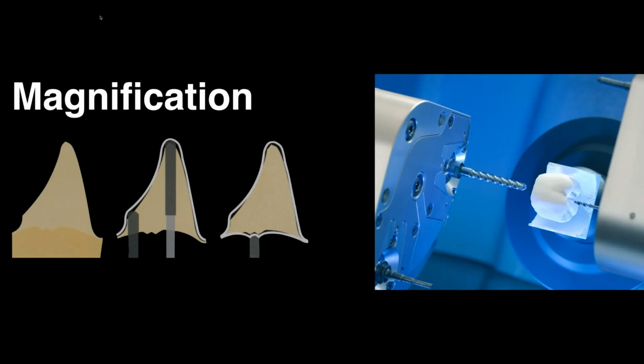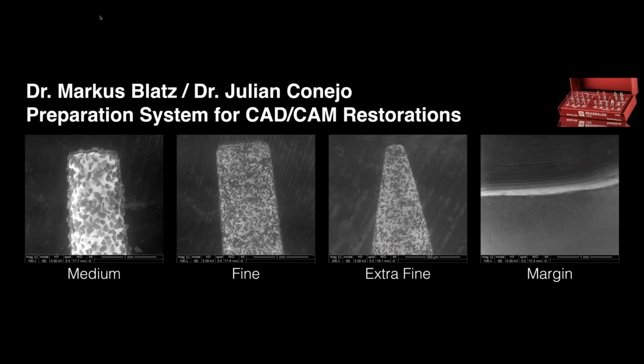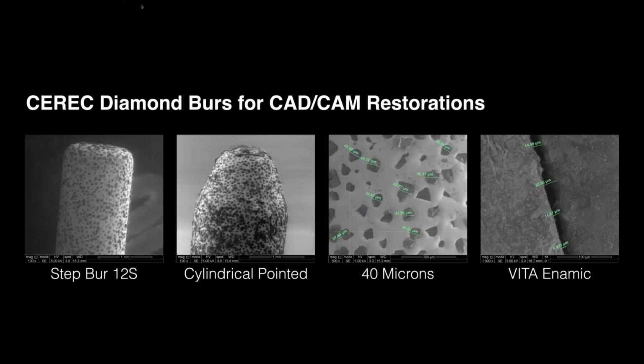Okay, so remember that no sharp angles for crowns, but also no sharp angles for porcelain laminate veneers. And when we use this sequence of a medium bur and then a fine diamond bur to prep, we are able to have margin adaptations, as you see here. I milled here some Enamic crowns for this study, and we could have even 11 microns of the gap between the restoration and the tooth. So it is possible to achieve excellent marginal adaptations with chairside CAD/CAM systems.